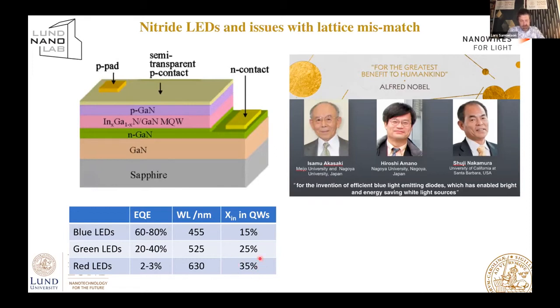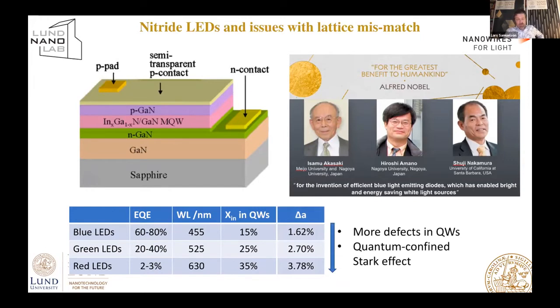The lattice constant differs from the gallium nitride substrate, typically 30%, 35% indium, and you are left with a single digit efficiency for most things that have been reported. So this, of course, has to do with the lattice mismatch. Here it is in numbers: for the blue LED, you have 1.6% lattice mismatch, for the green 2.7, and for the red 3.8. Which means that you get more and more defects in the quantum wells. You get the effect of the quantum confined Stark effect tilting the band structures. And you have effects from polarization phenomena that affect the device performance in a negative way.